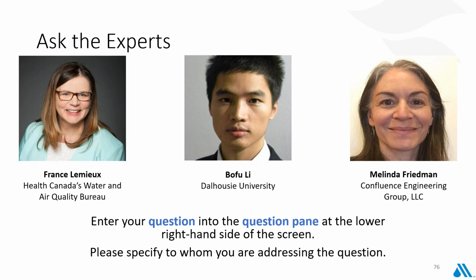I would add too that there's probably different answers to that question, whether we're talking about distribution systems versus premise plumbing. In either case, I agree, we would never substitute iron sampling for lead or other parameters if we're trying to understand lead corrosion. But we do a lot of work with main cleaning and correlating metals accumulation on surfaces and pipes, and we do see lead occurring in distribution system pipes. But in a situation where you have lead service lines feeding maybe galvanized plumbing, you could have quite high concentrations of lead on that galvanized plumbing, and if you're getting discolored water in those buildings, there could be more significant lead release there. So it is important to look at the whole picture, and they can be related, but yeah, agreed that I wouldn't substitute. I would just add maybe iron as an indicator in a system.